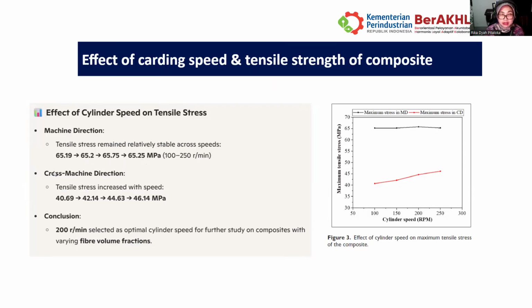65.25. And if we look at the cross machine direction, the tensile stress increases with the speed: 40.69, 42.14, 44.63, and 46.14 MPa. With all this data, the scientists concluded that the best cylinder speed was 200, which was selected as the optimal cylinder speed for further study.